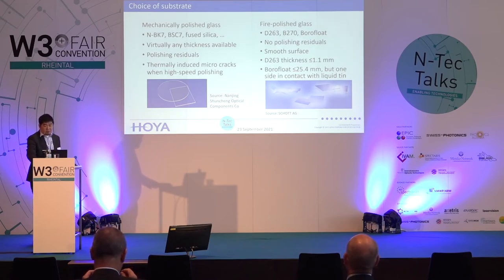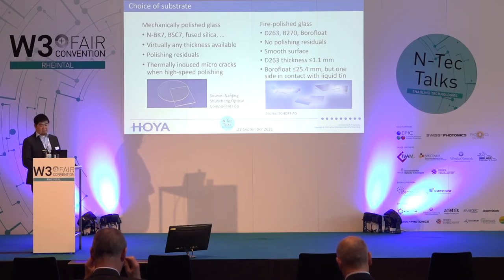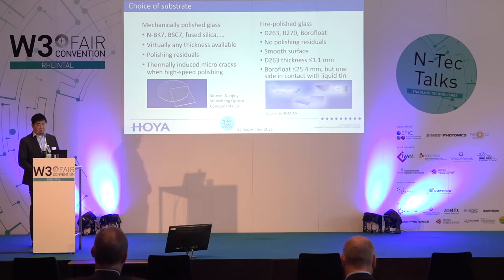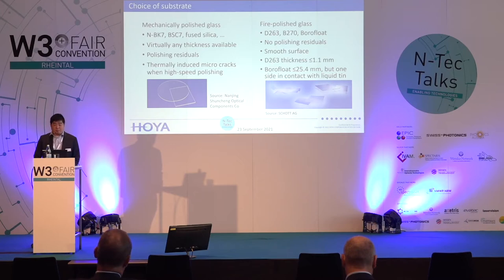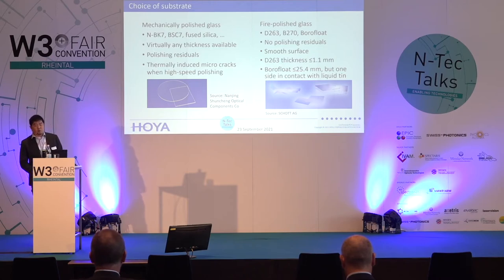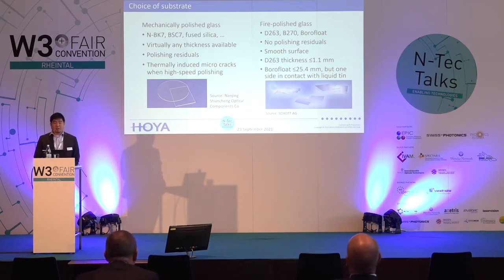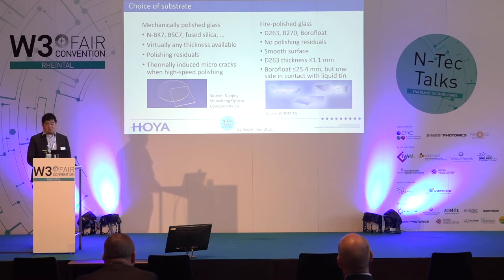The more complex the filters become, the more important the choice of the substrate. For many years, the standard, and still, is mechanically polished glass. They can be BK7 or equivalent, fused silica, or many other glasses. The advantage is that you can have them in virtually any thickness, but you might see that it's not always possible to remove all polishing residues, which can create a problem for the growth of the thin layers on the substrate. Of course, companies try to optimize production times, so they tend to use high-speed polishing, which might cause micro cracks on the surface.